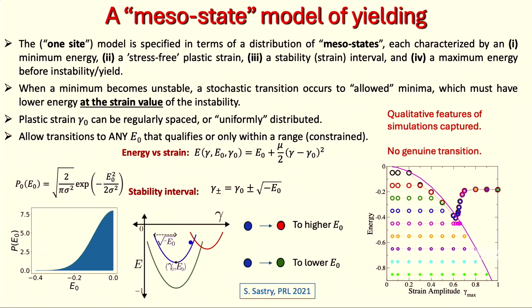So this is now a description of what happens if the system is residing in one of these states, and I change the strain on the system. With this description, I can then perform the dynamics and look at what happens from cycle to cycle to the energy of the system, just like what I described in the simulations earlier. And one gets a yielding diagram which looks qualitatively very similar to what one sees in simulations. There are interesting differences, but the basic features that are reproduced are, when I start with a poorly annealed glass, which is high energy, I have initial annealing before I yield as I ramp up the strain amplitude, whereas if I sit at a very low energy state, I do nothing till I reach some amplitude at which I make a discontinuous jump.